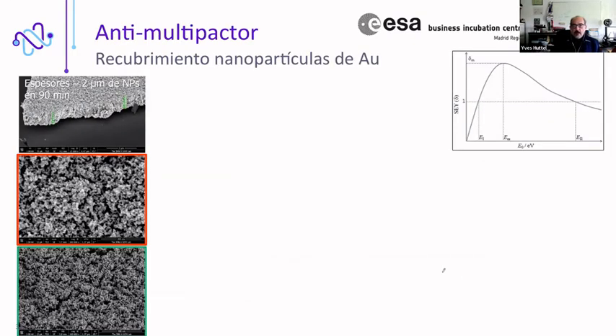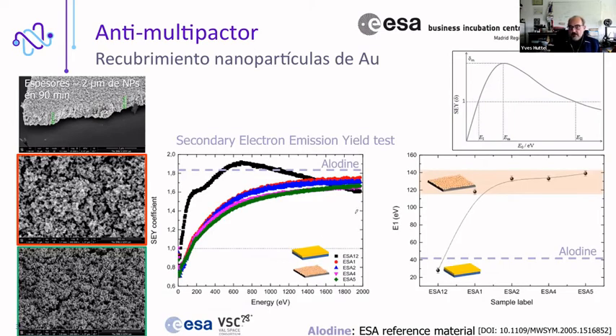Here are some examples of what we have done so far. Thanks to the high production rate of nanoparticles, we are able to make deposits of gold nanoparticles of several microns in a limited time. And we have found that these coatings made of gold nanoparticles are quite efficient in capturing the electrons.